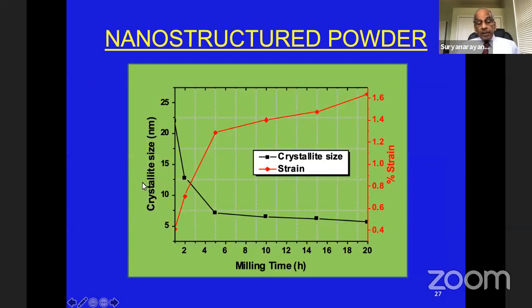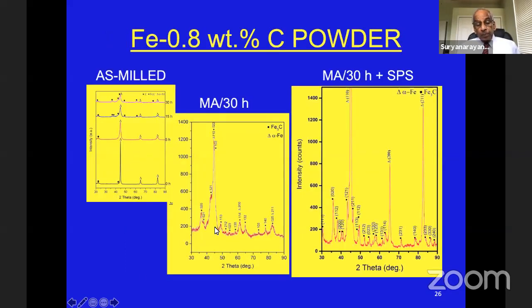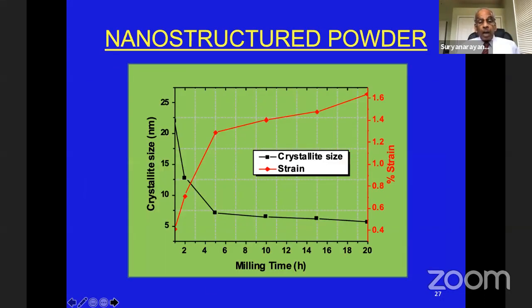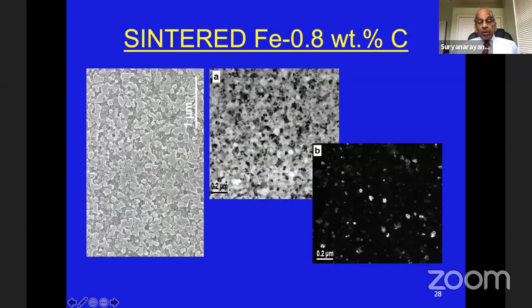The grain size decreases continuously and reaches something like about 6 to 7 nanometers. And the strain in the powder increases. And these are the two reasons why the peaks in the previous plot, for example, are very broad. So all those are gone by spark plasma sintering. Now, if you look at the microstructure, in the SEM, this is the way the microstructure looks like.